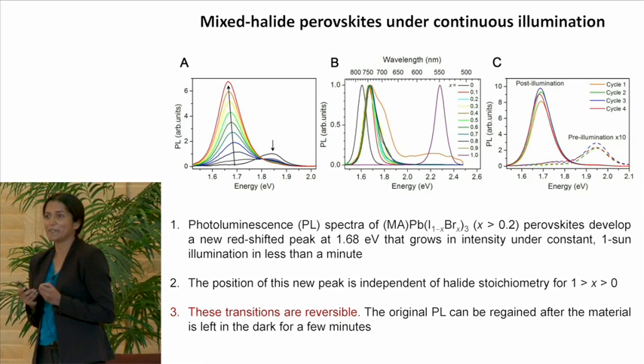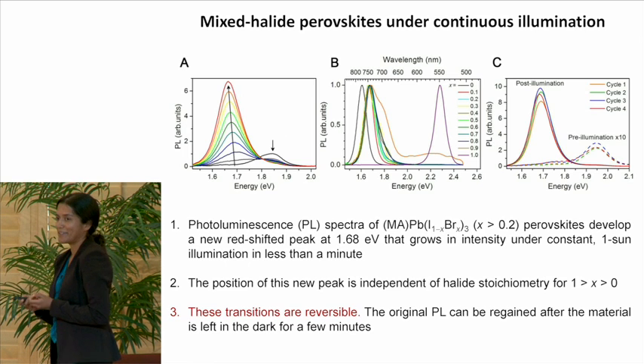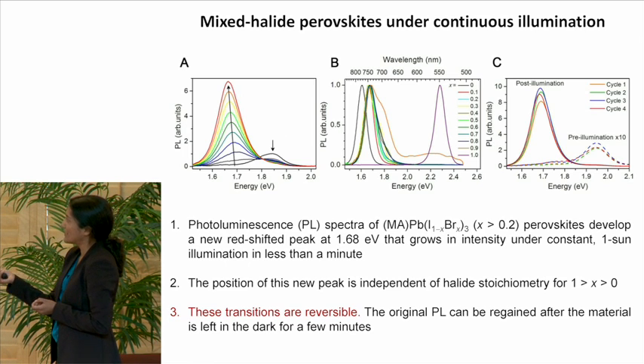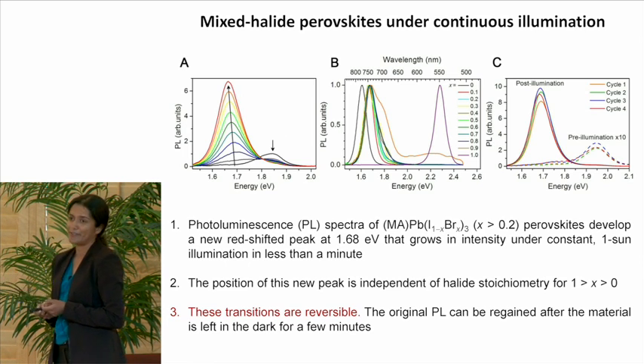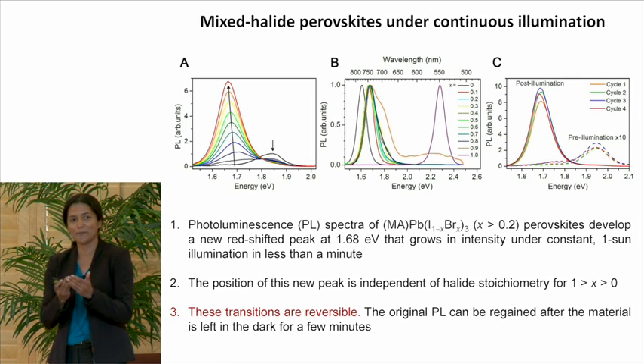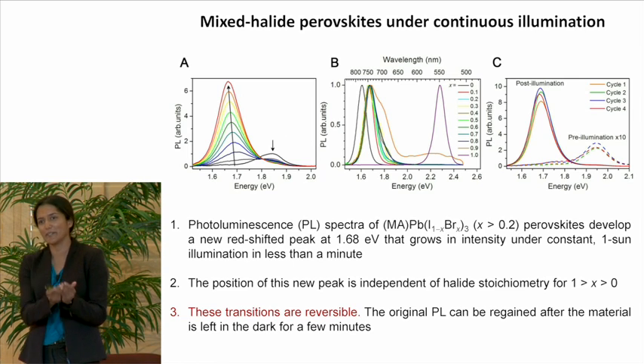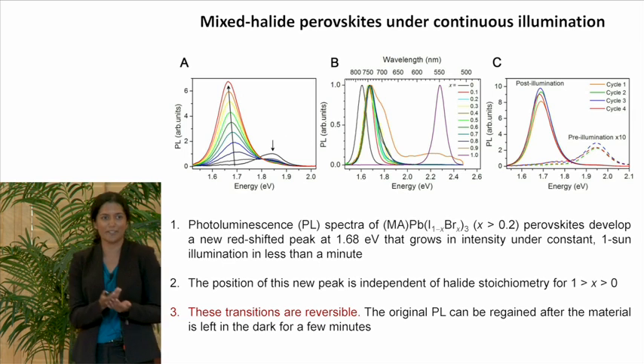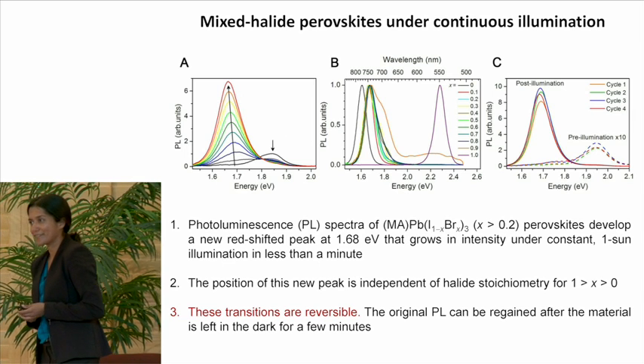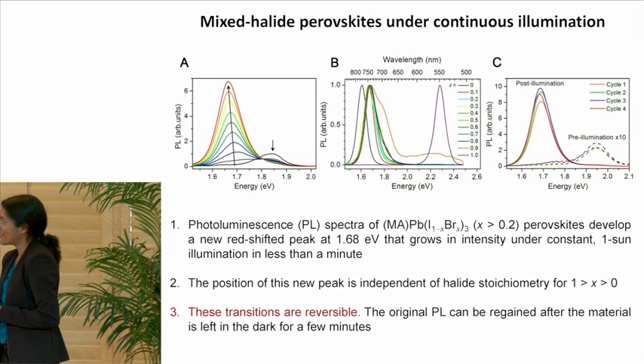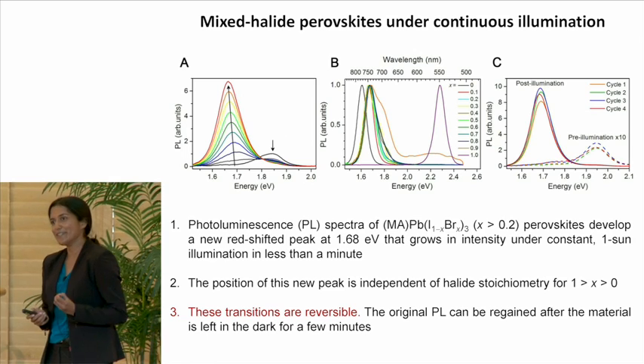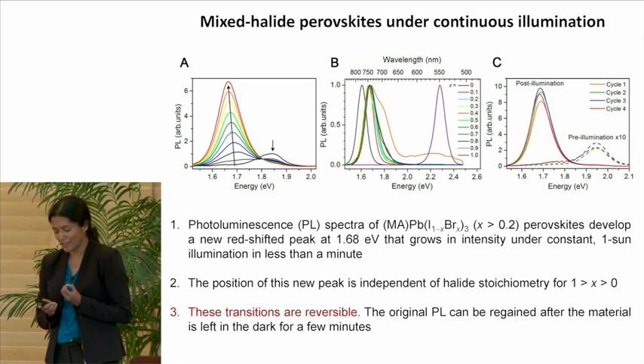And what's really surprising to me about this transformation is that it's reversible. When you turn off the light, you regenerate the initial material, and when you turn on the light, you get this new low energy PL, and you can cycle between this. Eric has done this several times. Here I show you data for 4 of these cycles. So we decided to study this material under illumination to figure out what on earth was going on.